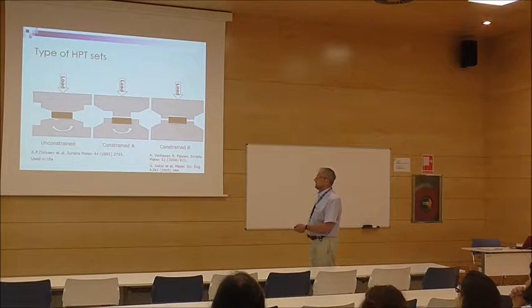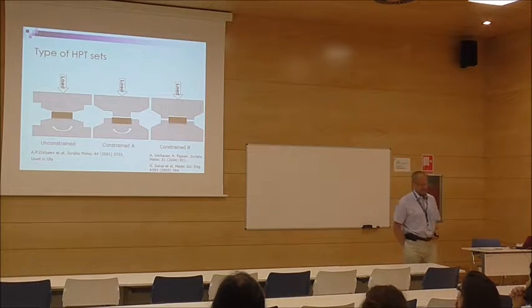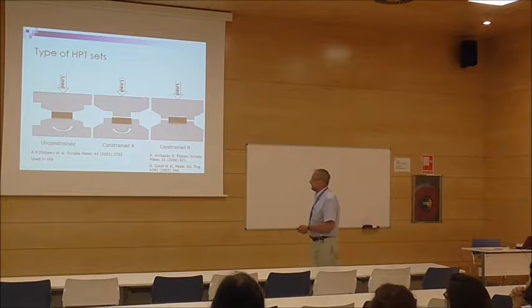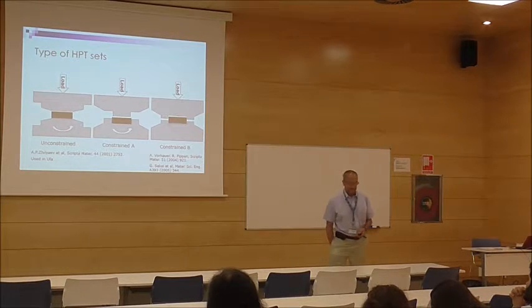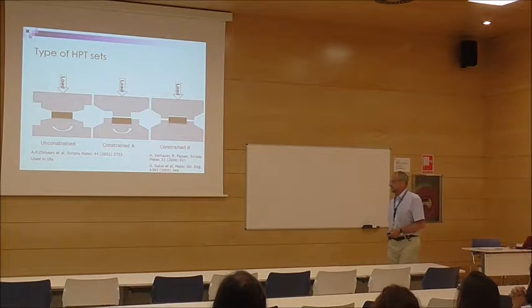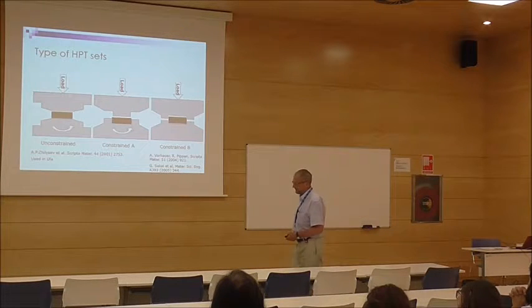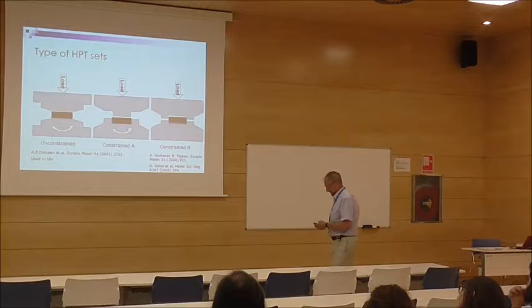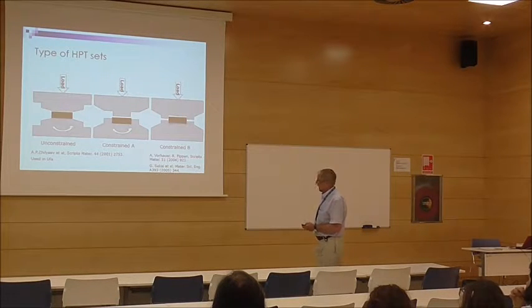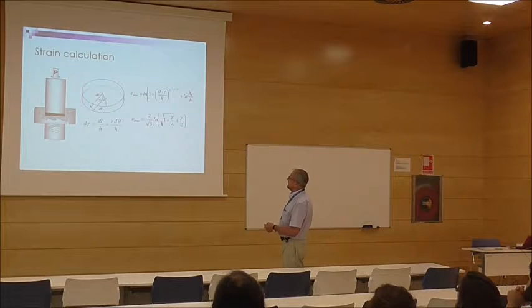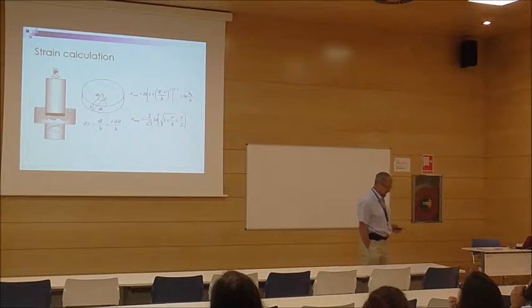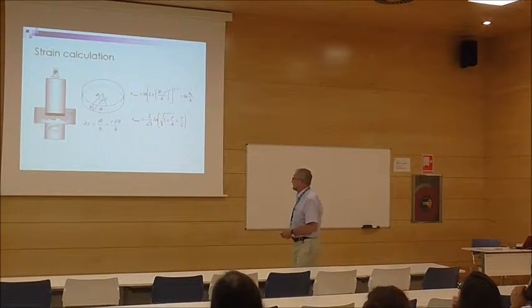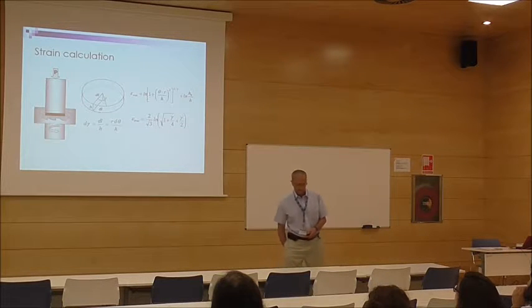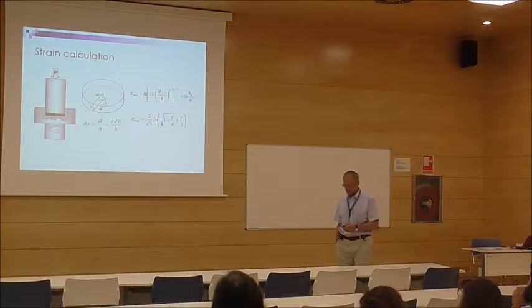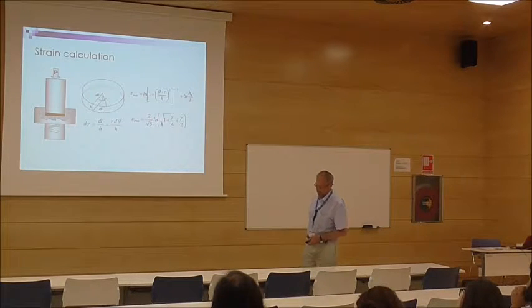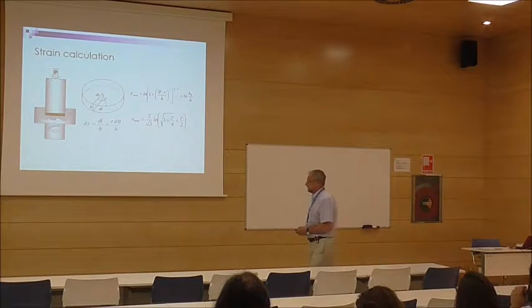And in this case, you will get very thin samples, like 0.1 millimeter, not very suitable for tensile properties. In the other cases, you will get thicker samples, like 0.8 millimeters in thickness, from which you can cut miniature, micro samples to test tensile properties. This is the strain calculation. It's very rough, based on the geometrical approach. Probably it's not very correct, but anyway, some people use this one, calculating equivalent strain by the von Mises equation, which was actually developed for very small strain, not suitable for large strain.